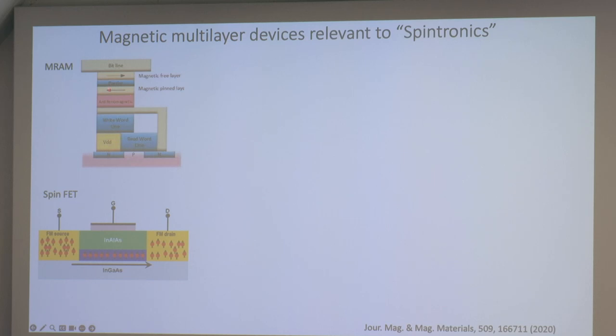And this works by having the spin from one layer diffuse into the other layer and rotate the orientation with an electrical current. So you want an electrically controlled spin device. And to do this, you have to have spins, controlled electrically in one layer going to the other layer and rotating it. So it's required to have some sort of layers where you can manipulate spins to have any sort of device like a memory device. Even this famous spin FET, for example, is ferromagnetic sources across another material with a ferromagnetic drain, and you can change the orientation of the ferromagnets. So the best control you can have of spintronics type devices is having multiple layers where you control the magnetism in different layers to build up these sort of systems.